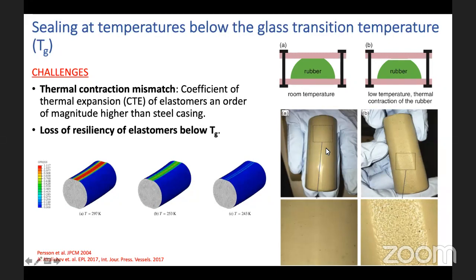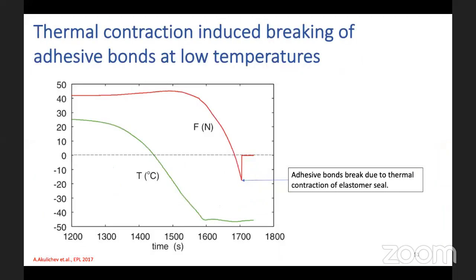Suppose you have an O-ring and you compress it at room temperature, and then you will form a leak path, and also you will basically freeze in elastic deformations. So in rubber, the elastic deformation is frozen in, and then that will also cause leakage. So if you see force as a function of time, when the temperature is decreasing from ambient to below -40, you will see that